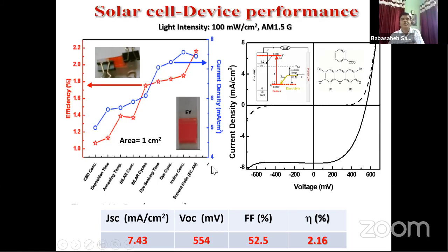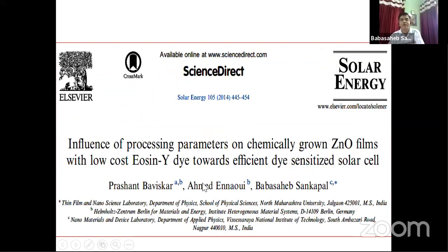All these results are published in the Solar Energy journal, where you can get an idea about how to adsorb the dye, how much time it takes, and how much efficiency it is possible to achieve. These are based on the influence of the processing parameters on chemically grown zinc oxide by using the low-cost eosin Y dye. Eosin Y is a very cheap dye. For example, 25 grams of this dye costs about 700 to 800 rupees.